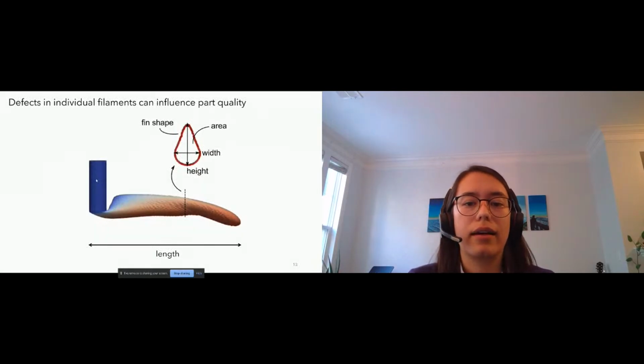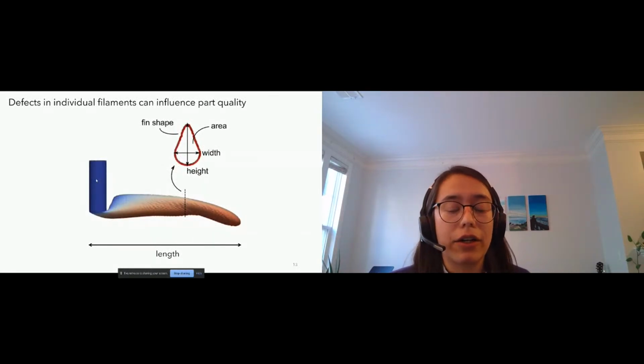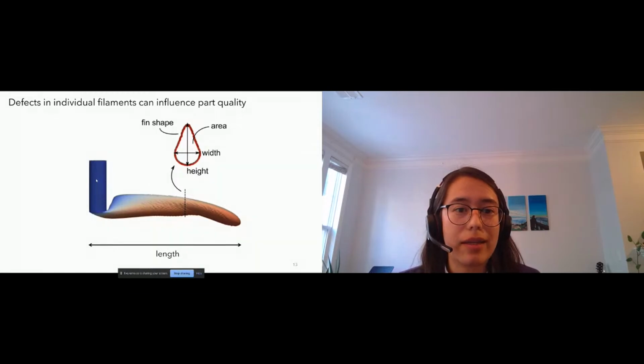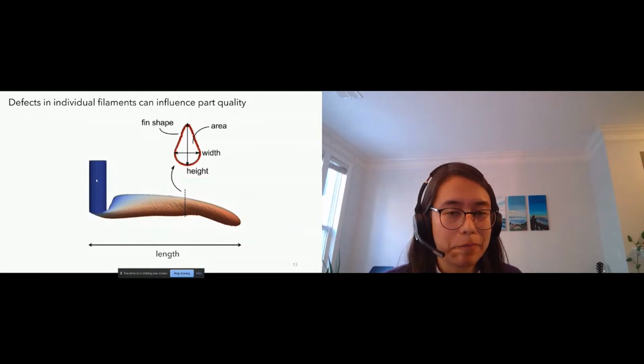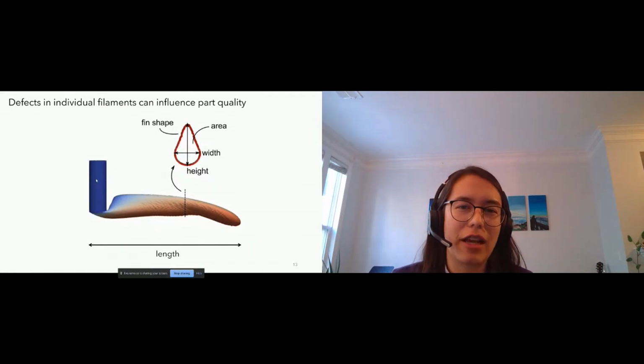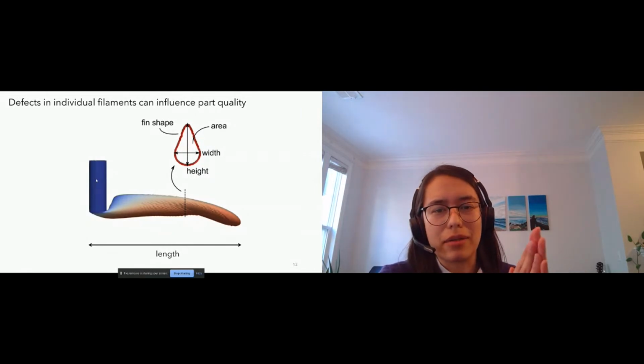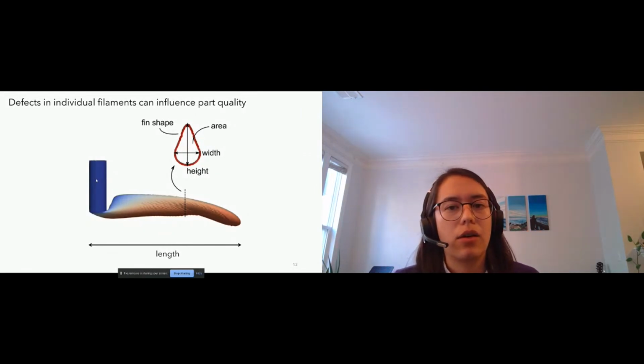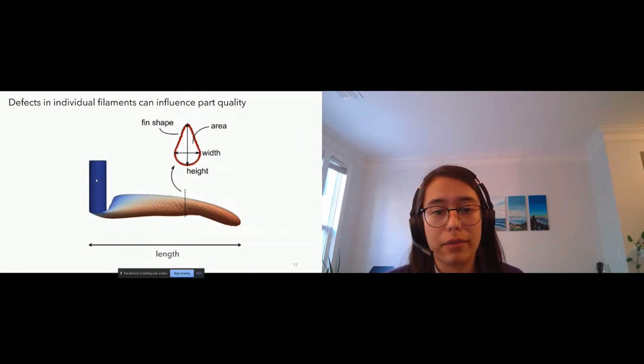So I'm going to talk about how defects can occur in individual filaments in embedded 3D printing. So this is a simulated filament. You can see that blue column is the ink that's inside of the nozzle, and you have a filament that's coming out of the nozzle. If you look at the cross section of that filament, it's not circular like the nozzle is. It actually has a sort of fin shape. So it narrows towards the top and towards a point. So I'm going to express that cross section in terms of the aspect ratio, the height over width.